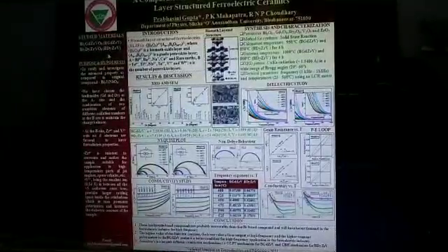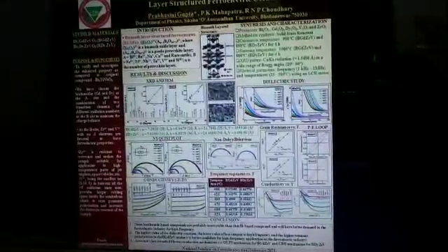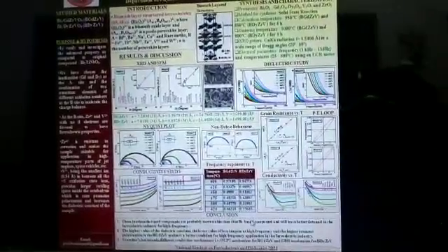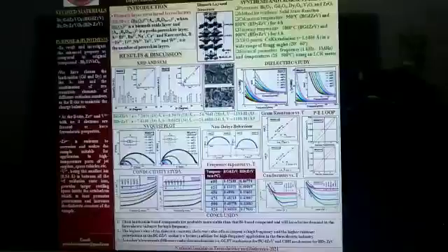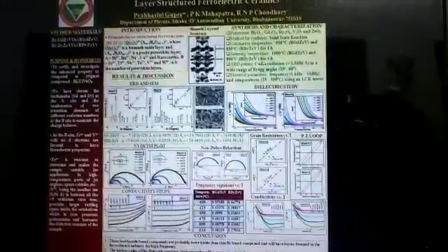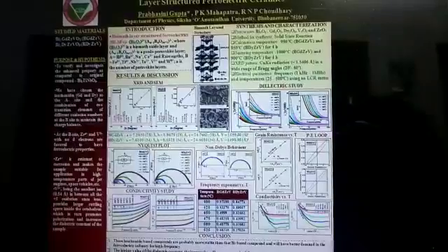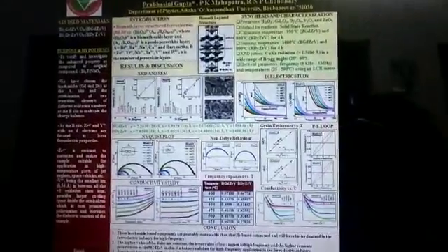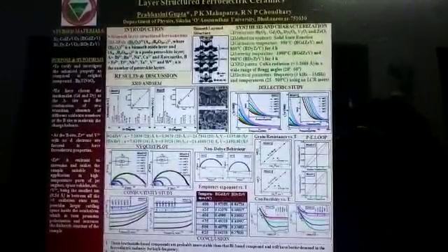Here I have synthesized two BLSF materials, Bi2GdZrVO9 and Bi2DyZrVO9. The purpose and hypothesis of my work is to verify and investigate the enhanced property as compared to the parent compound Bi3TiNbO9. As there are no reports on the substitution of Gd and Dy in the BLSF compounds, I have chosen these lanthanides at the A site and the combination of two transition elements of different oxidation state at the B site to maintain the charge balance.